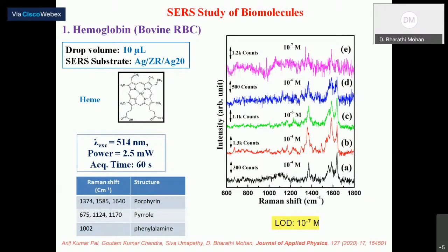Then we use these substrates for the detection of hemoglobin, and the hemoglobin we have prepared with the drop volume of 10 microliter drop casted on the substrate, like the silver-based 3D structure. We used a Raman spectrometer with the excitation wavelength of 514 nanometer, the power supplied 2.5 milliwatt and acquisition time of 60 seconds. And this hemoglobin is prepared with various concentrations. As you can see, it is prepared from 10 power minus 4 molarity to 10 power minus 7 molarity to study the limit of detection.